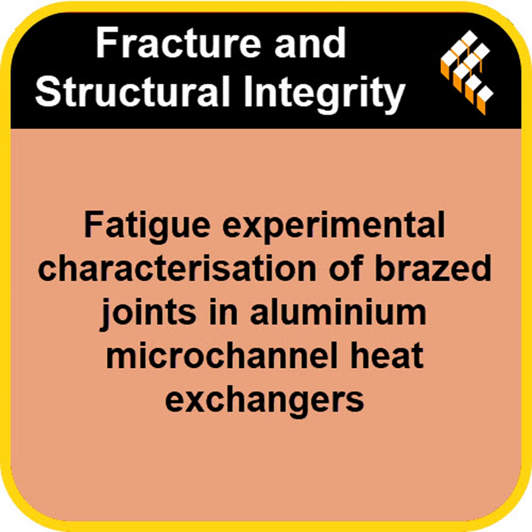Aluminum naturally forms a very tough, stable oxide layer on its surface almost instantly. This oxide layer prevents the molten filler metal from properly wetting and bonding to the base aluminum. So the flux is there to clean the surface somehow. Precisely. The flux contains chemicals like these potassium and cesium fluorides that aggressively react with and break down that aluminum oxide film at the high brazing temperature, allowing the filler metal to flow and create a good metallurgical bond.